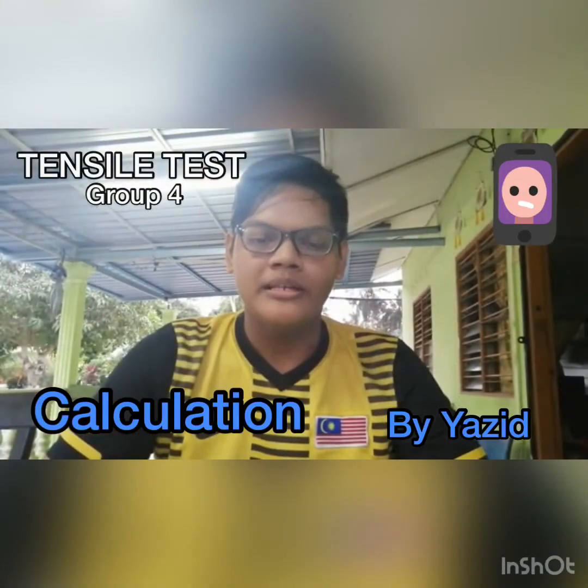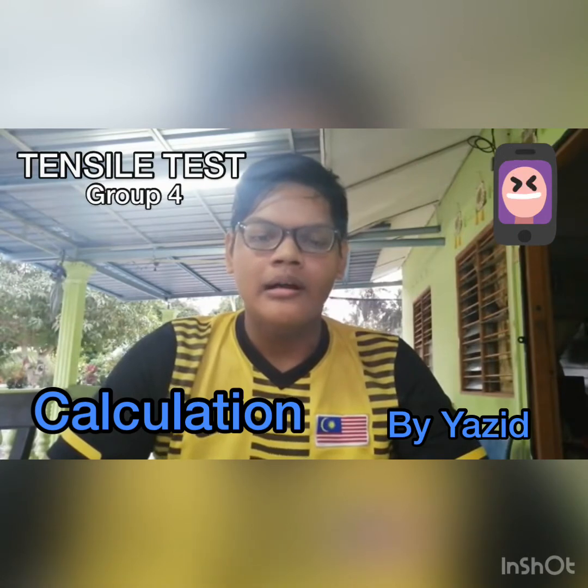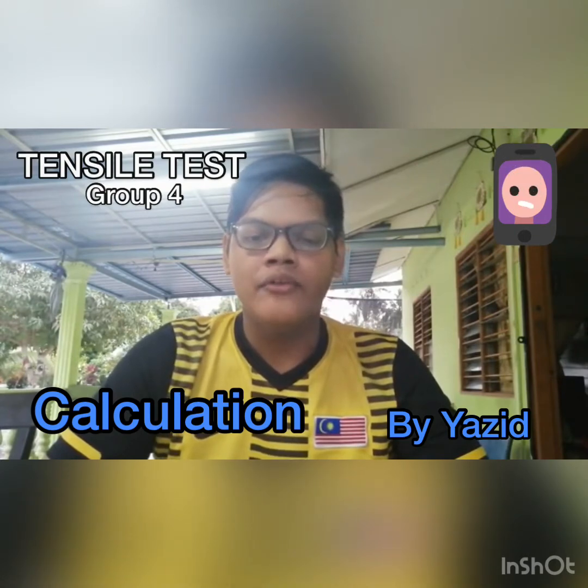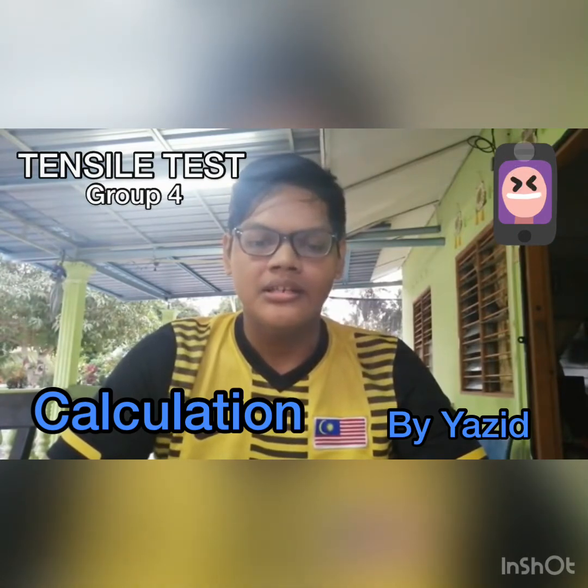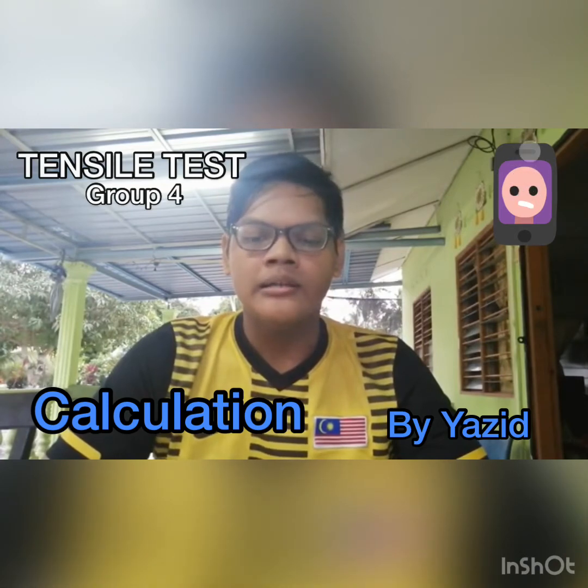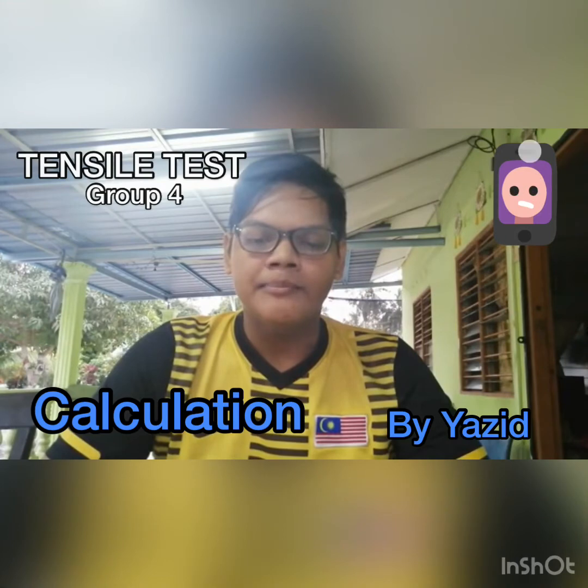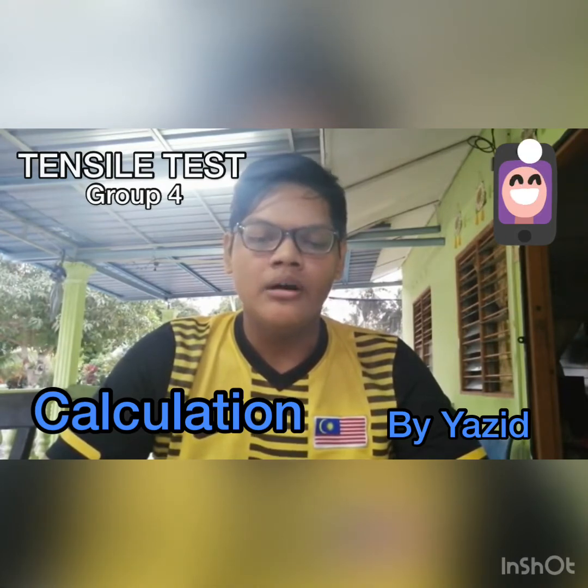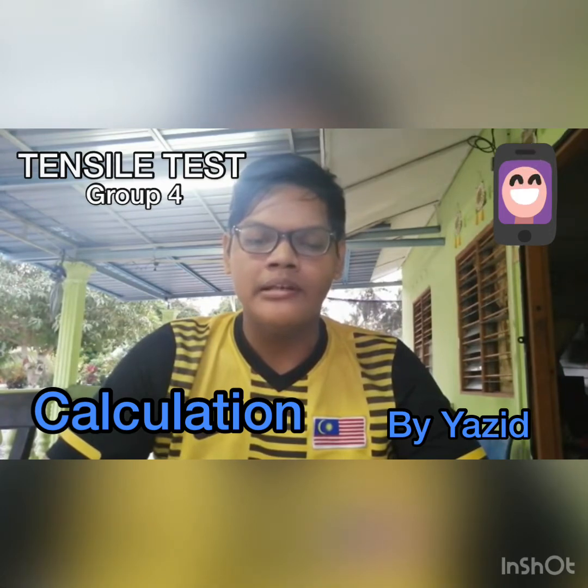My name is Muhammad Yazid. Now, I will explain about the calculation for the tensile test. First, we need to calculate the Young modulus from the graph of stress versus strain, the percentage reduction of area, and the percentage of elongation. For the mild steel, the stress from the graph that we got is 554.27 MPa and the strain is 0.037.